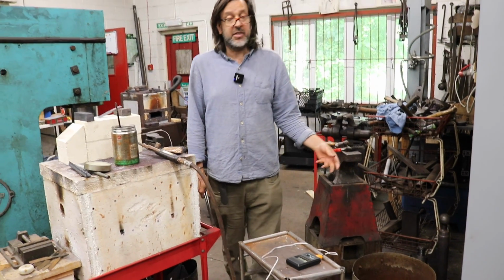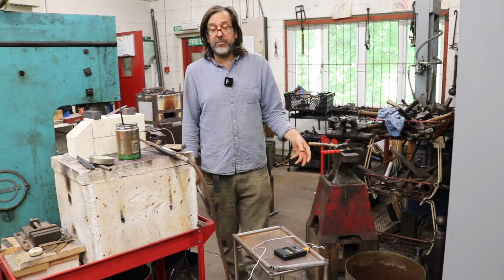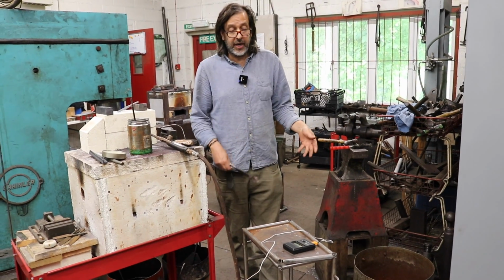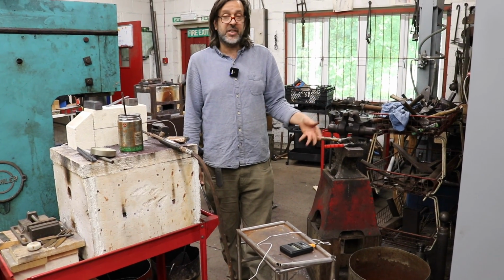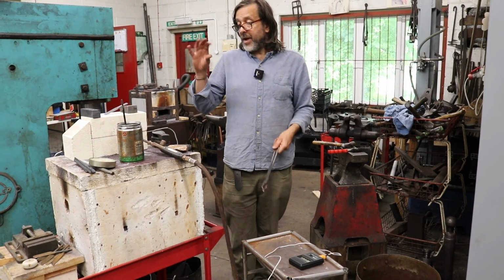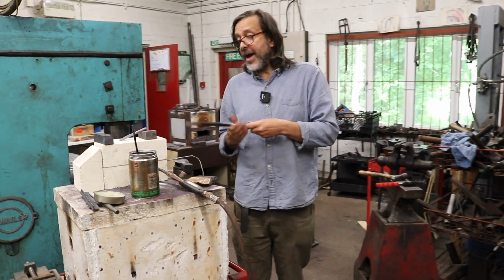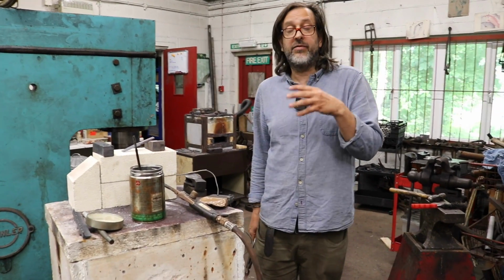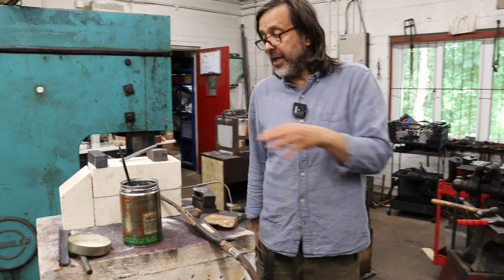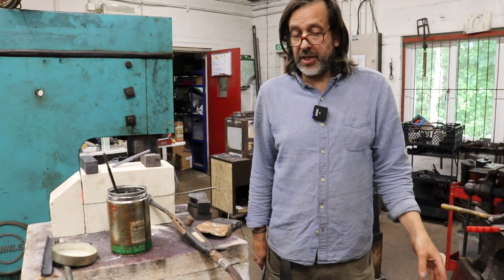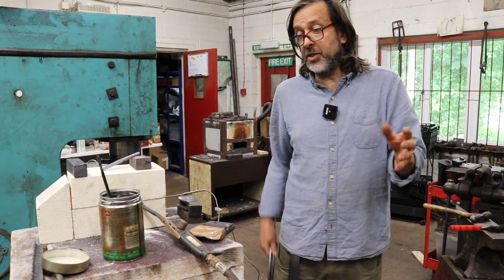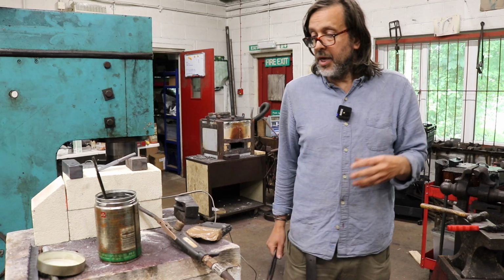You can actually increase that by putting salt in the water and making a brine, and it will cool even quicker, but your chances of busting the steel are much higher. Bearing steel has enough alloys in it that it will harden effectively in oil, so we're going to use oil. It's very risky hardening bearing steel in water, and not necessary because you get enough hardening in oil.